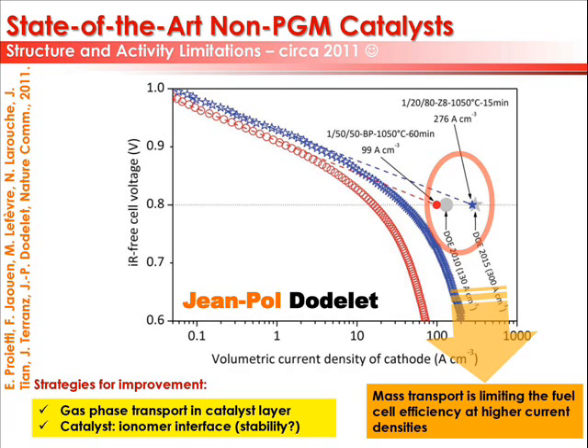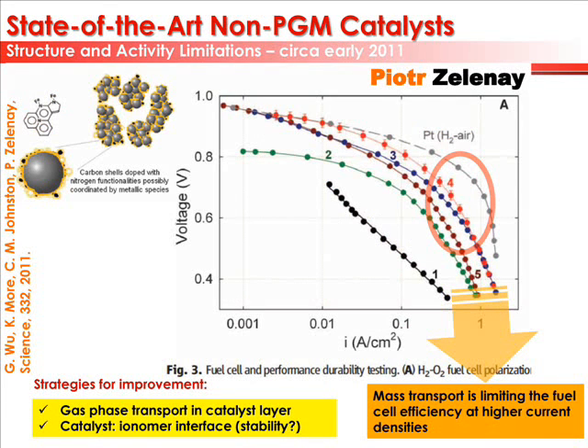And the purpose is actually to start from a catalyst, whatever, some poor one. You start from something, and then make it better. And the way to make it better is to make the second site more active and less selective. So essentially decreasing selectivity and increasing the activity towards hydrogen peroxide will shift you here. And then the second is increasing the stabilization of hydrogen peroxide on the site will shift you here. If you just allow yourself to understand that things are not as good as you promise, it can give you the opportunity to make them better. If you only start by thinking that you have just discovered everything, you will never make your catalyst better. Okay, that's my little thing.